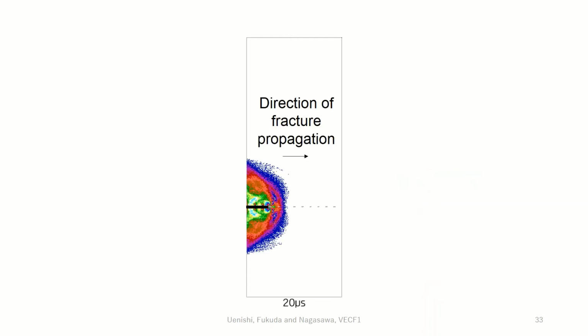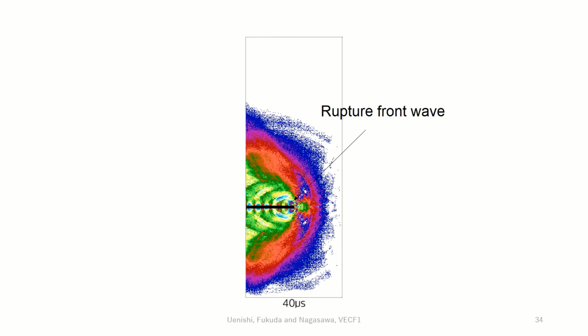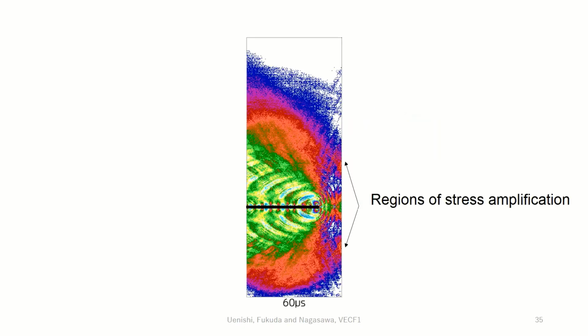The primary fracture propagates at an experimentally observed speed of 563 meters per second from left to right. Around the tip of the primary fracture, the so-called rupture front wave develops. At this stage, regions of stress amplification can be identified at positions away from the primary fracture plane. At these amplified regions, the secondary fracture will be initiated.